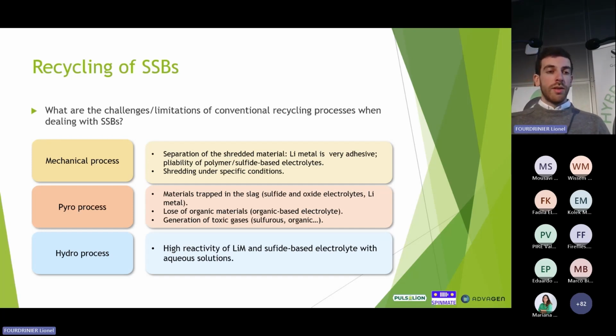Also, some materials would be lost, like the organic materials, because you burn them during the pyrometallurgical process, and also you would have a generation of toxic gases like sulfurous gases, organic gas. Regarding the hydrometallurgical process, I mentioned that in solid-state batteries you can find similar chemistries in the cathode to the ones we find in the current batteries. But still, we have to take into account that we have the lithium metal and we can have sulfide-based electrolyte. So you need to consider this when designing your hydrometallurgical process to see which kind of aqueous solutions you will use in the leaching and how it can interact with these materials.